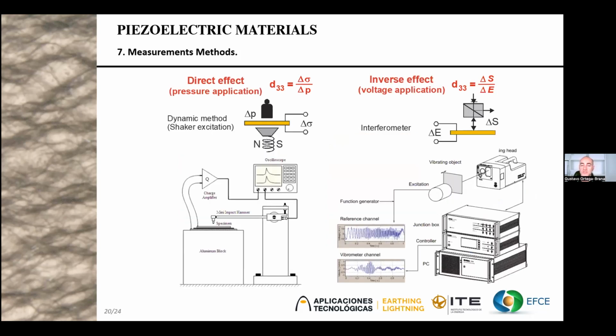The dynamic method by mechanical excitation is an alternative for frequencies under approximately 20 kilohertz. The setup is quite simple because it needs a shaker, an oscilloscope, and a charge amplifier, and we can characterize the piezoelectric coefficient. The inverse effect can be measured by laser interferometry: the laser hits the surface of the sample and measures the deformation of the sample when an electric field is connected. With that, we can characterize the resonant frequency of the material, which corresponds to maximum displacement. In the case of polymer foam, the displacement is on the order of nanometers or a few micrometers.